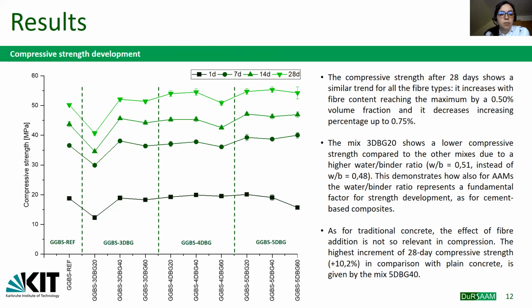The compressive strength drop you can see on the left of the graph corresponds to the mix with 20 kg per cubic meter of Dramix 3D fibers, and this is due to a different water binder ratio. For this mix, in fact, a water binder ratio of 0.51 was used instead of 0.48 as for all the other mixes. The different water binder ratio is related to the utilization of wet aggregates, and it can also help demonstrate that also for alkali activated material, the water binder ratio plays an important role in the compressive strength development.